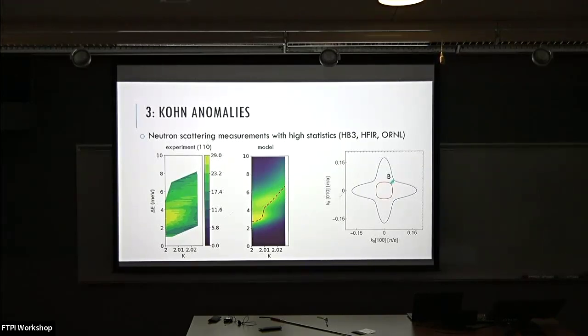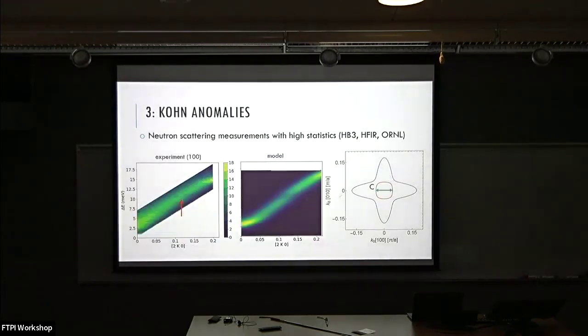And again, the statistics on these measurements is huge, so it's really reliable data. In principle, we should be able to do much better deconvolution. This is just an initial thing. And then finally, there's also a hint of the C. Now, this inner Fermi surface has a much higher Fermi velocity, which would make the Kohn anomaly much smaller. But again, if you do a super good neutron measurement, then you can see maybe something happening.